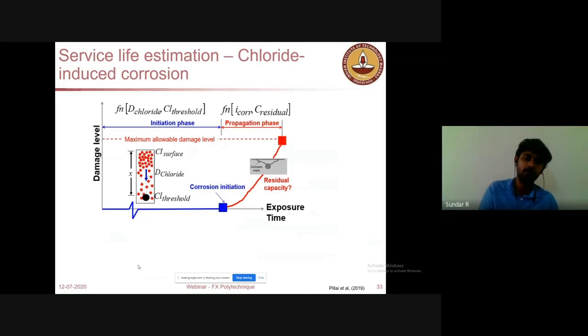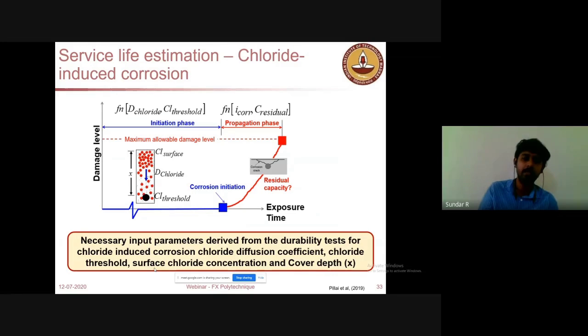So here I want to define service life first. You should define the service life based on either the initiation period or the propagation period. Normally, initiation refers to the time taken for a sufficient amount of chloride to reach the level of the steel to initiate corrosion. This is a longer period of time. Most calculations consider corrosion initiation as the end of the service life. However, corrosion propagation can also go on for up to 6 to 10 years, and you can still work with this propagation period to extend the service life.